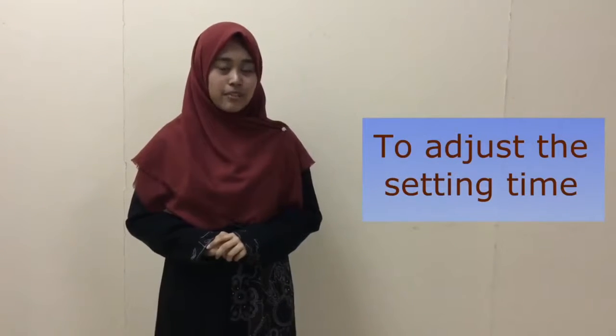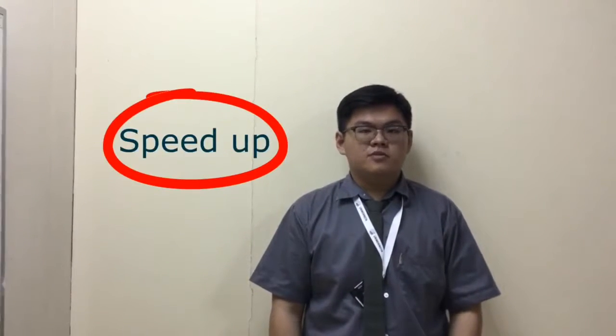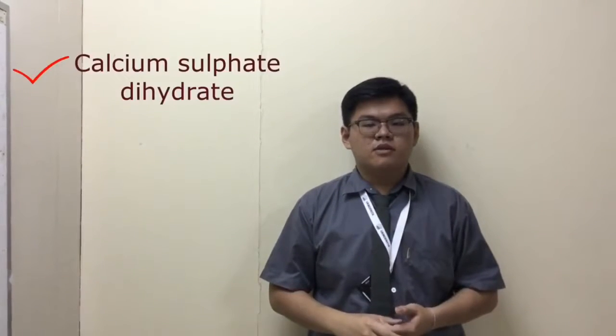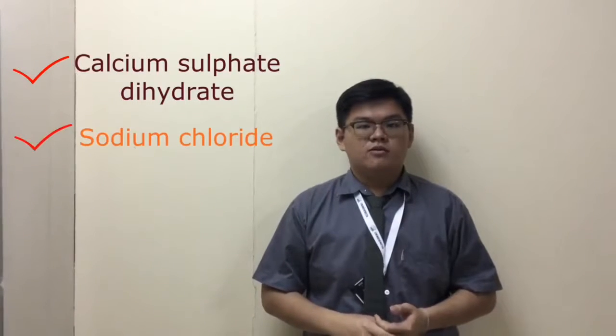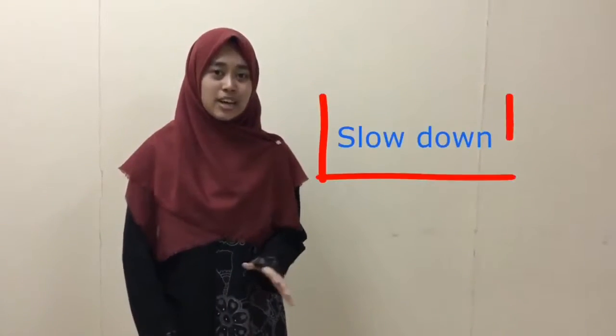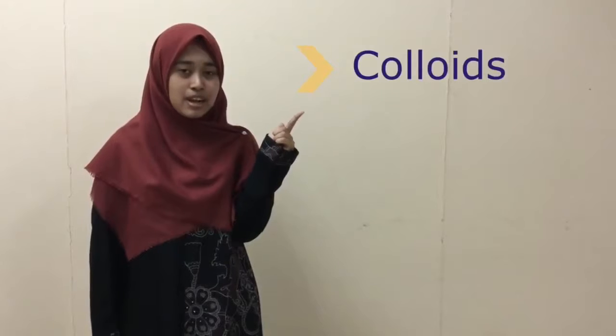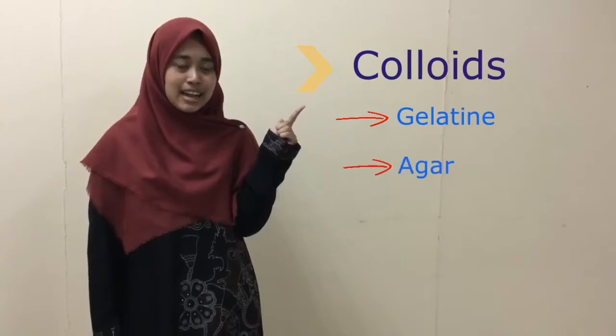To adjust the setting time of gypsum product, we have accelerators and retarders. The function of an accelerator is to speed up the hardening of a gypsum product. Examples of accelerators used in gypsum product are calcium sulfate dihydrate, sodium chloride and also potassium sulfate. The function of retarders is to slow down the hardening of gypsum product. There are 3 examples of retarders. The first one is borax, the second one is colloid. Examples of colloids are gelatin, agar and glue, and the third one is gum arabic, acetates and also citrates.